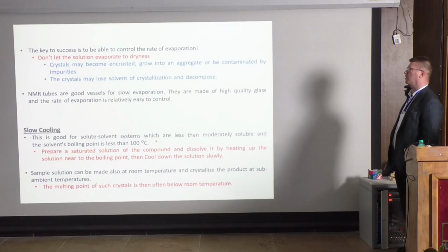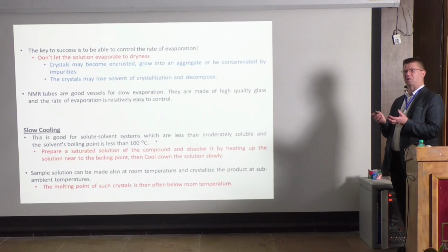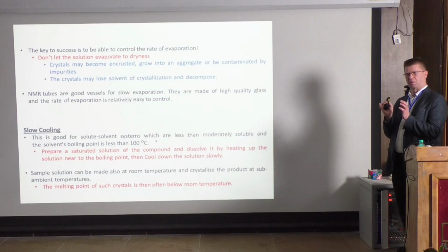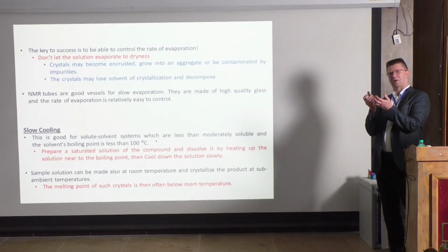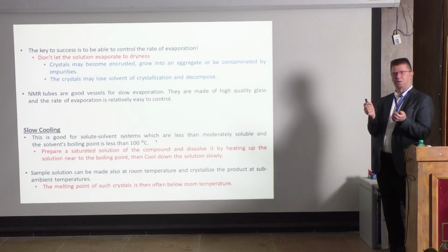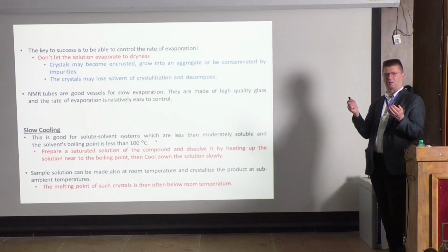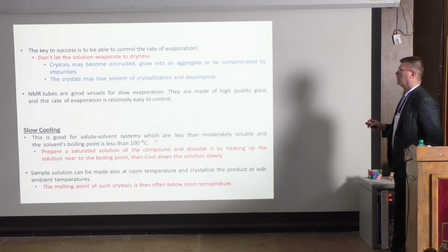This is actually what I indicated. And in some cases, it happened many times to me too, that by accident it went dry, but then the crystals had formed on the wall of the tube, and when you tried to take them out, they were glued in there. When you try to take them out, they crack. So it was really frustrating. Very nice looking crystals, probably very good single crystals. But when you take them out, when they dry, they die. So they crack. And that's the idea.